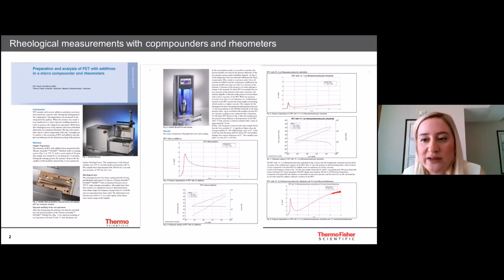And in the third trial, you see PET with 2 different additives again. And here we see a completely different structure. The pressure is increasing up to 55 bars, which is also related to the structure forming. And we can also have the data from the oscillation measurements, which correlates with these results. So as a conclusion, we can say that it's possible to have rheological measurements directly in the compounder during the processing. But of course, if you go for further testing or want to broaden the range, we need an advanced rheometer system.